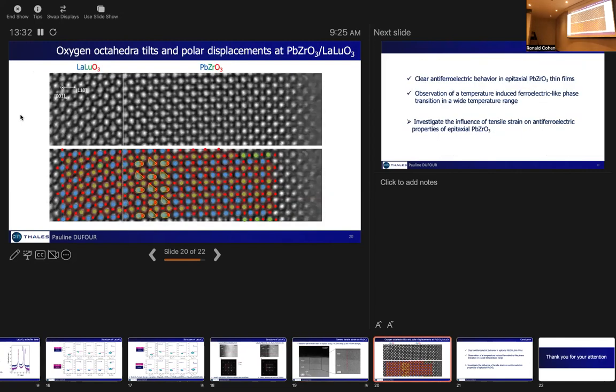And this is what we intended to do with the 4D STEM measurements. So on the left, you have the LLO, and on the right, you have the PZO. And you can see that at the interface, you have indeed a symmetry conforming of the lead zirconate toward the LLO. It will intend to reproduce the same oxygen octahedral tilting. And actually, we have seen that quickly you have a gradient of this oxygen octahedral tilt that emerges, until 6 unit cells, after which you have no more oxygen octahedral tilt.